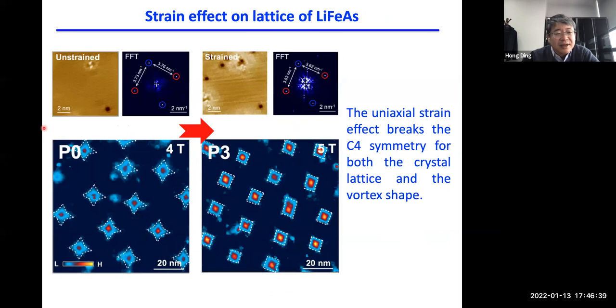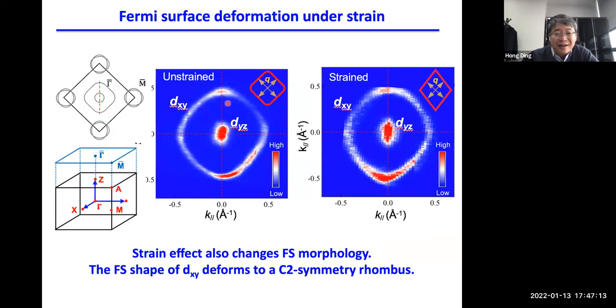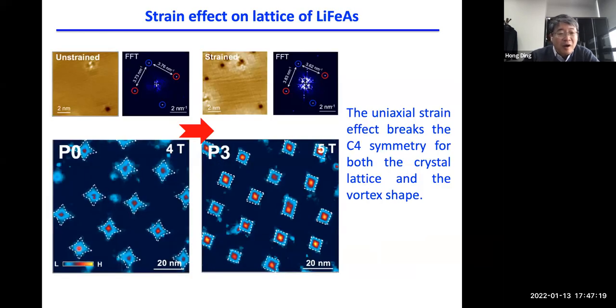We also see in STM this axis change from being the same to being quite different. So you can clearly see the difference from the C4 to the C2 lattice. And also you can see from the image of the vortex that the C2 case has this star shape, which is a signature of this large square d_xy state. This gives the tip of this star. And if we